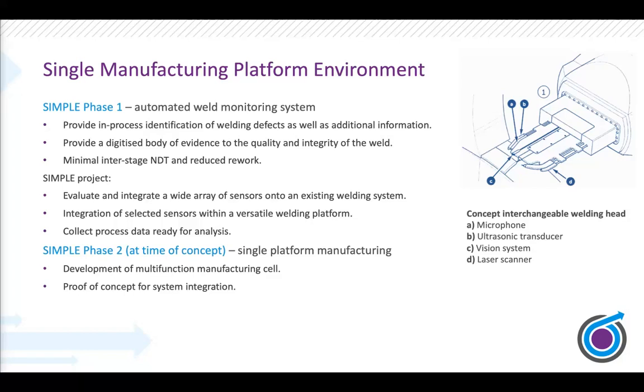But this workflow is established so that you don't get to your final inspection, then find that you've deposited a flaw at the root of the weld, then have to grind through 100 mil of previously deposited weld, and then go through a very arduous repair strategy.